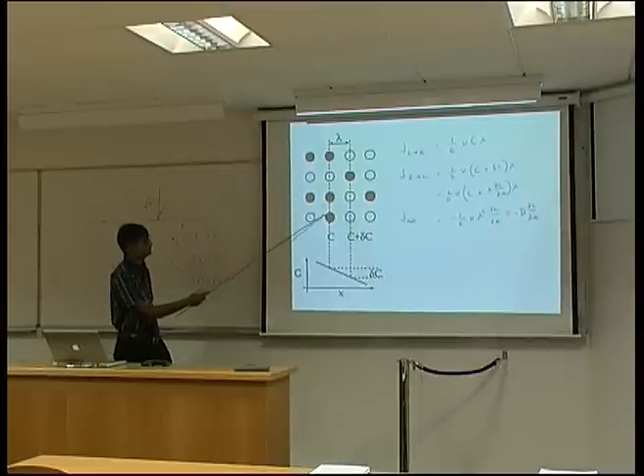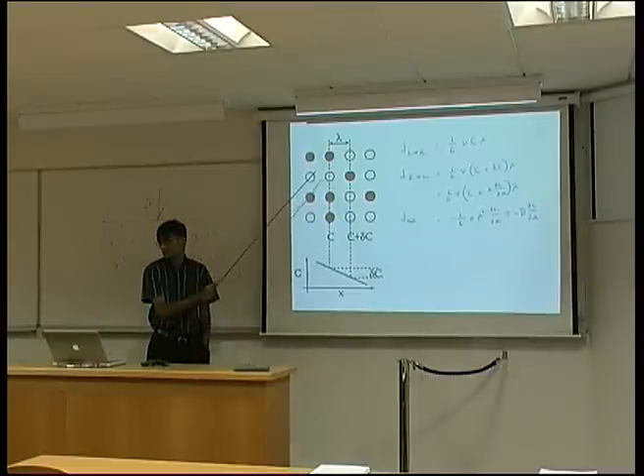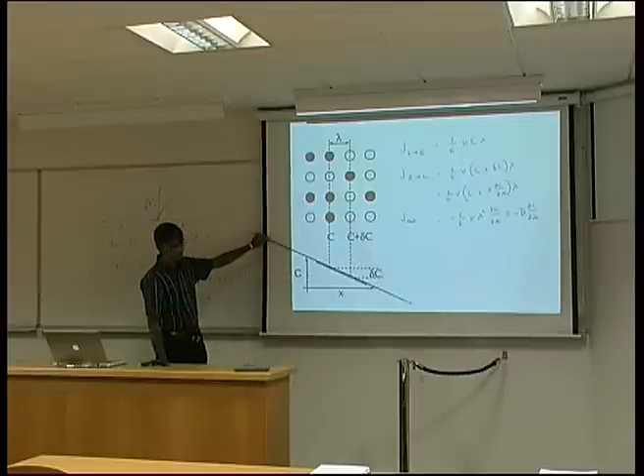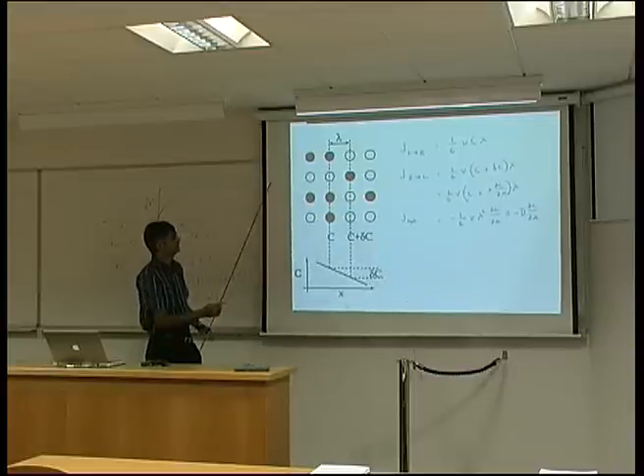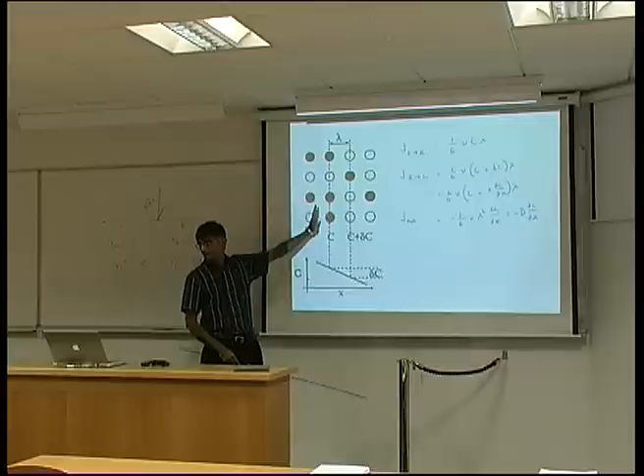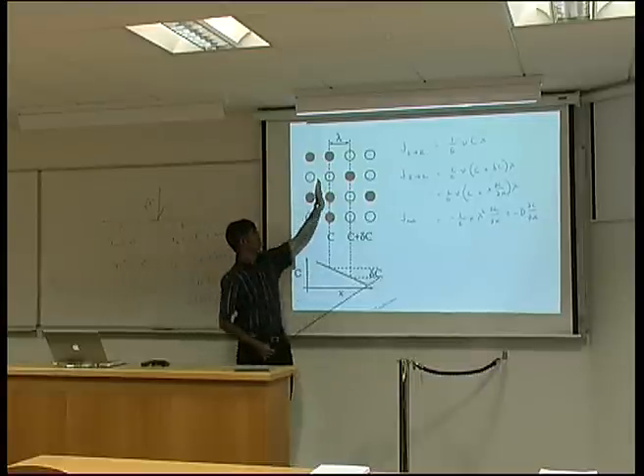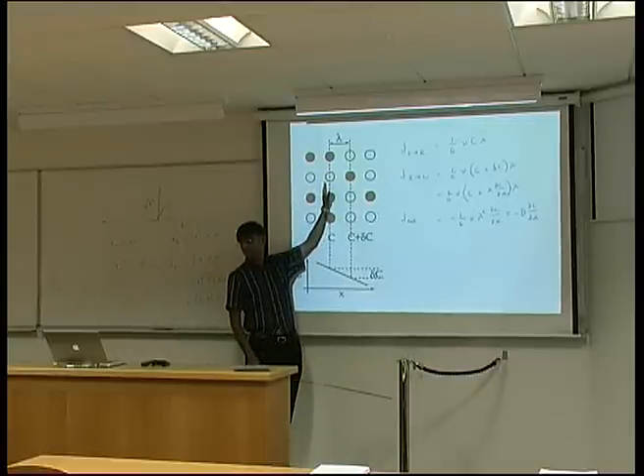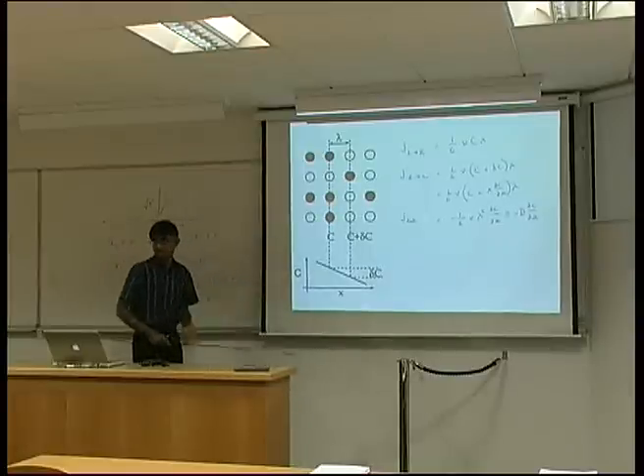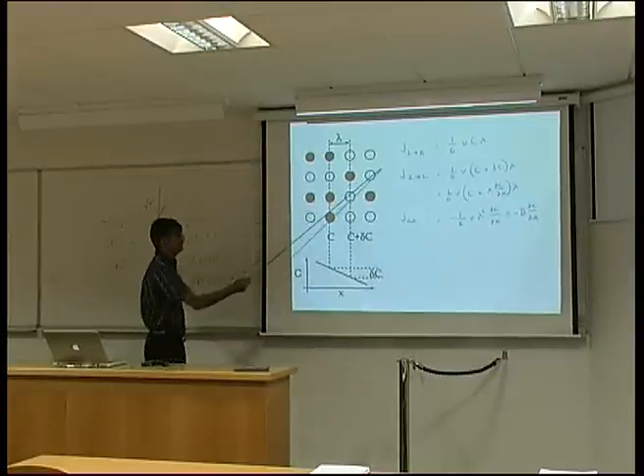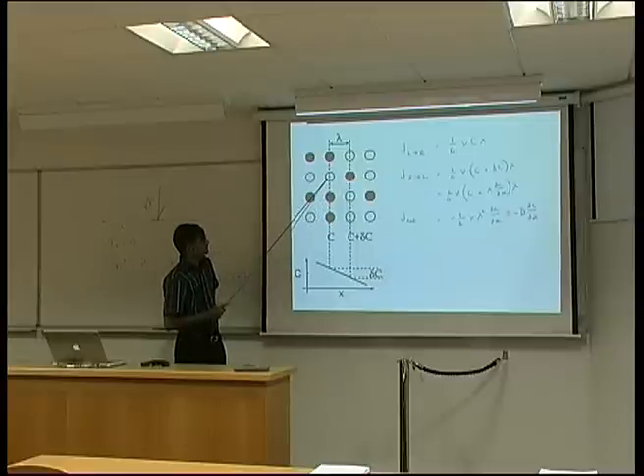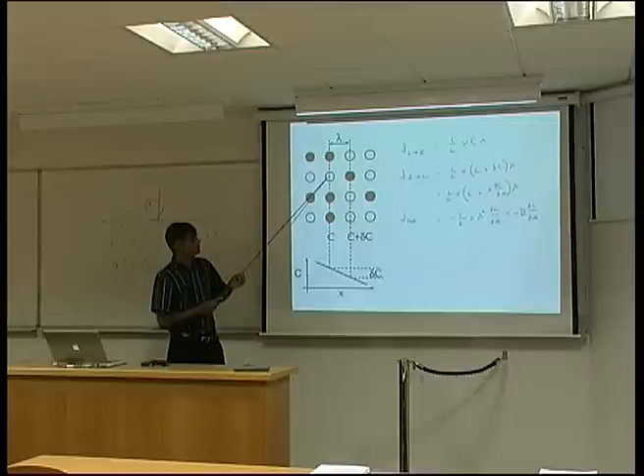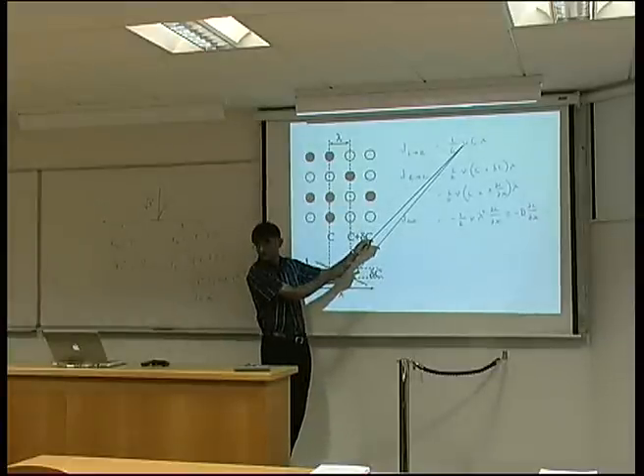And you can see that the concentration of atoms here is different from the concentration of atoms here because we are moving down this gradient. Now, we will assume that each one of these planes has a unit area, so the jumps are happening across a unit area. We can now write the flux of atoms from the left to the right-hand side as being proportional to the jump frequency. It's attempting jumps from one plane to the other, so we have a jump frequency here.